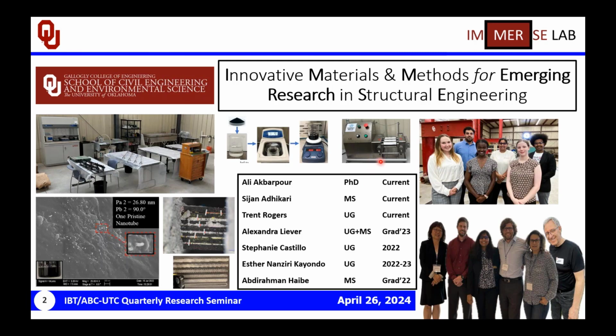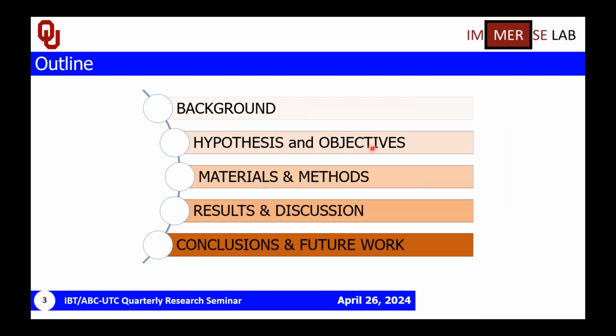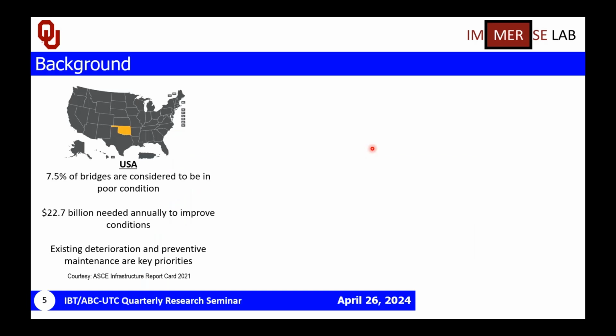Coming to the condition of infrastructure currently, we have 7.5% of bridges that are considered to be in poor condition. And looking at the monetary aspect, a $22.7 billion value is needed annually to improve these conditions. So really the existing deterioration and preventative maintenance are the key priorities in our infrastructure outlook. But if you look at some of the most important chemical and physical factors that affect durability and strength, we have different attacks of sulphate, levels of exposure through a sulphate environment, alkali silica reactions, seawater effects, acid attacks, carbonation, chloride attack, and freeze-thaw effects.